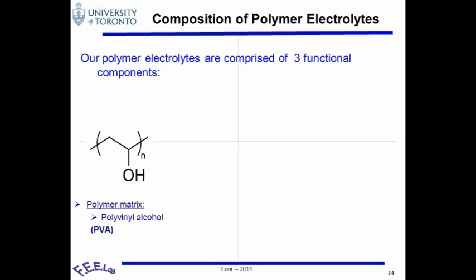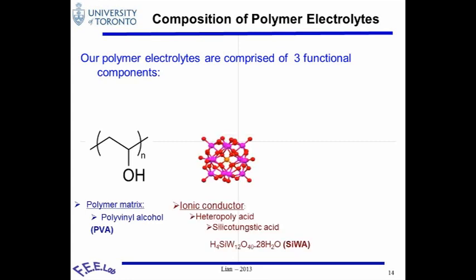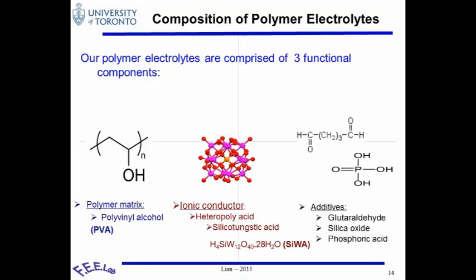One is the polymer matrix, using polyvinyl alcohol in very small amounts. The majority of the electrolyte is actually silicon tungstic acid, SiWA, which is our ionic conductor. To further improve conductivity, we've also introduced smaller molecule additives for different purposes that we'll talk about.